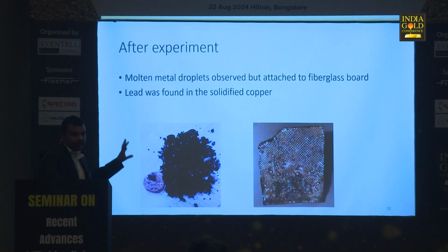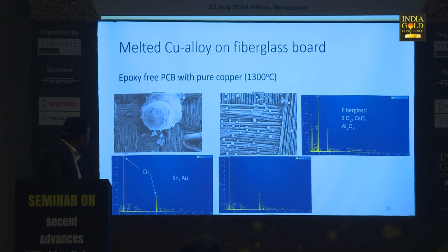You can see this woven structure, which is essentially the fiberglass that is there. If you look in detail, these are microscopic images, very beautiful images, showing that the copper has indeed melted, but could not be separated from the fiberglass because those are very small droplets, and it's a woven thing, so it is not able to percolate through and go into the melt. You can see this is copper. There is a small gold peak here as well, but primarily it is copper and tin. And of course there is some fiberglass, which is essentially SiO2, Al2O3.